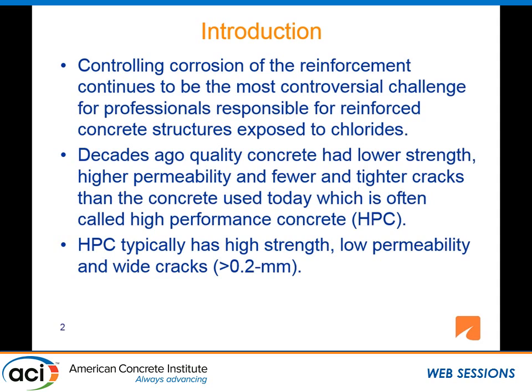And I can go to bridges right in Charlottesville, Virginia, go under the decks. Back in the early days, we weren't using stay-in-place forms. I can go under some of these decks, built in the 60s. There's not a crack in the concrete deck, still today. High-performance concrete we use today typically has high strength, very low permeability, but unfortunately a lot of wide cracks.